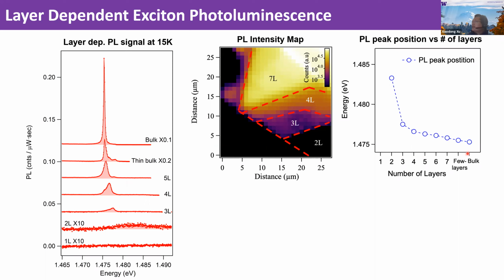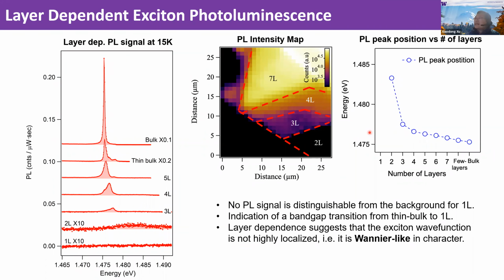We can also extract the peak intensities and the peak positions as a function of layer thickness, as shown here. The data shows that as we reduce layer numbers, there's a blue shift of the exciton luminescence. There are a few points we can take from these measurements. First of all, there's no PL signal in the monolayer, and this indicates there's an electronic structure transition from thin bulk all the way to monolayer. Also, the exciton signal has a strong layer dependence in terms of intensity and energy. This means that the exciton wave function is not highly localized. It depends on the interlayer couplings, so this is a Wannier-like character for the excitons.